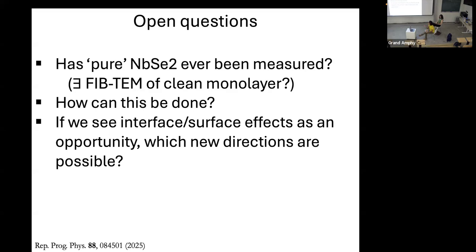Again, with hBN, I would raise the question of whether there is any moire happening between hBN and whatever is placed on it. I mean, it is a hexagonal material. No, of course. People discuss this, aligned, not aligned. This is important for the structural challenge later. For the FCIs, you need this more. But if you don't want anything for a substrate, I think it's very hard to find a substrate that gives you nothing.